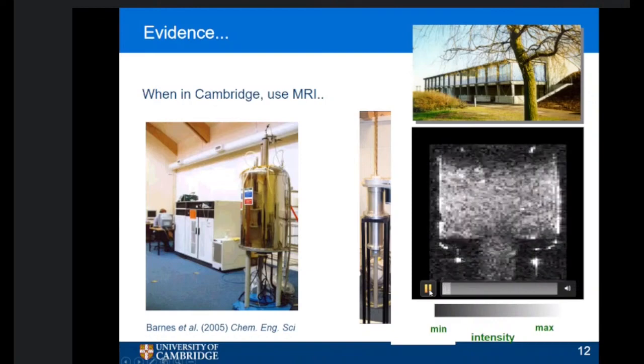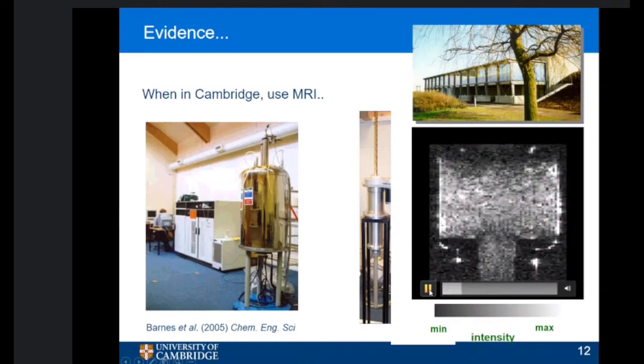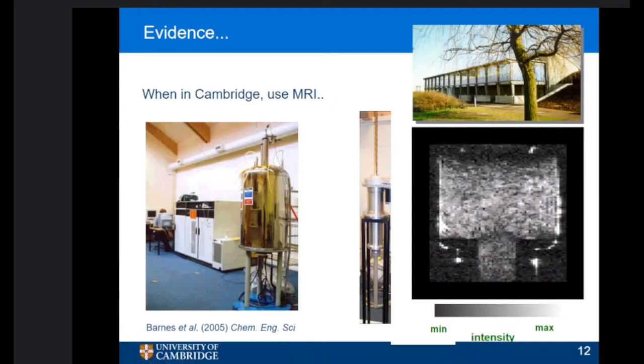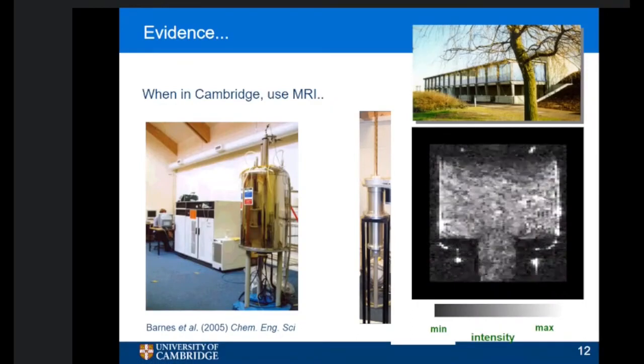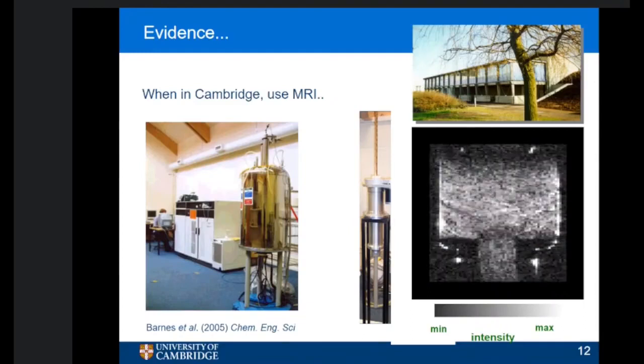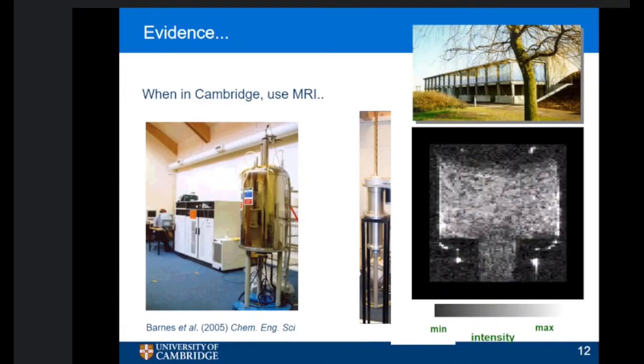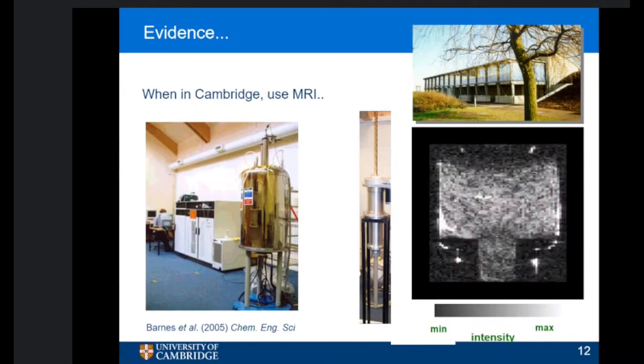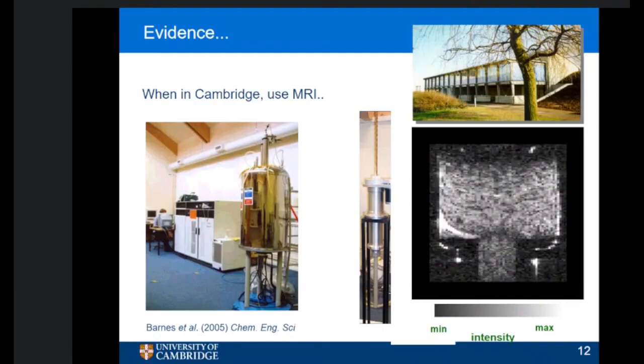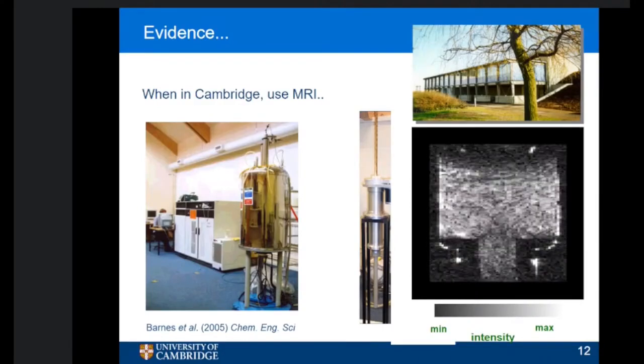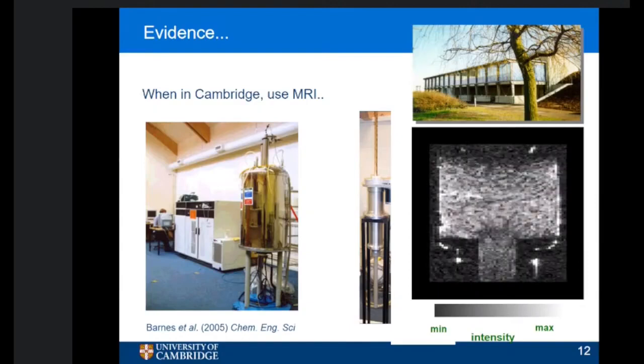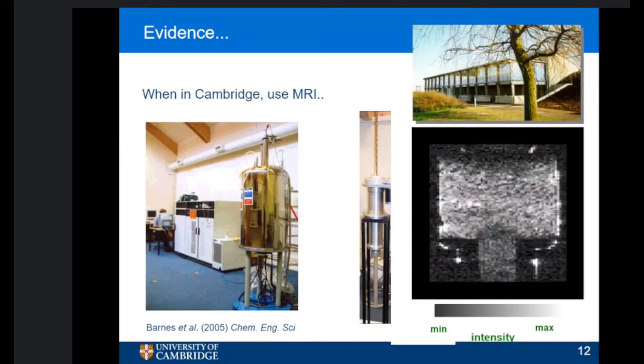So what you can see is those bits of black, white, and gray are changing, and that's related to the material inside there flowing. You can't really tell a lot from this image because of the way that the data are collected. But the important thing is that for each of those pixels, we can work out the local velocity, which means we can map the velocities inside this system. The other thing you can see is that this stuff isn't the same color everywhere, and that's because this is a paste, and these are quite irregular systems. So there's a lot of noise in the data. Anyway, we got the video to work, so I'm very happy.